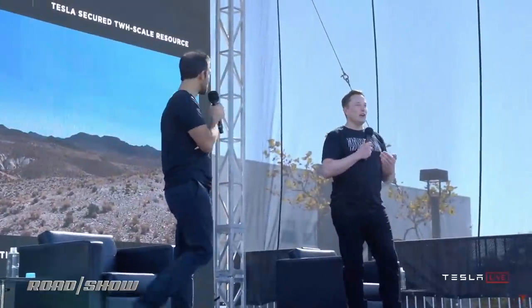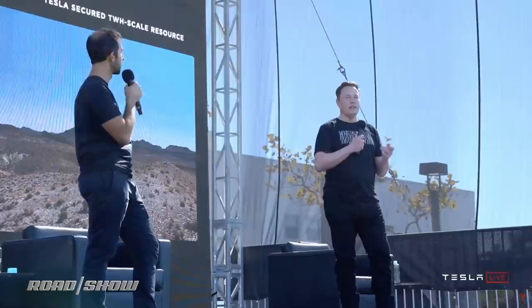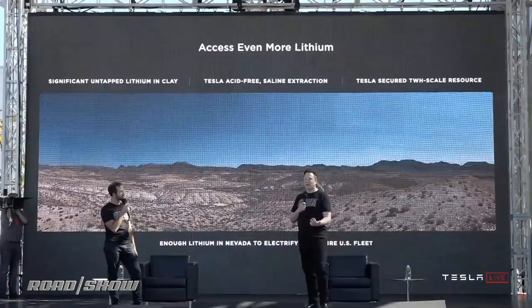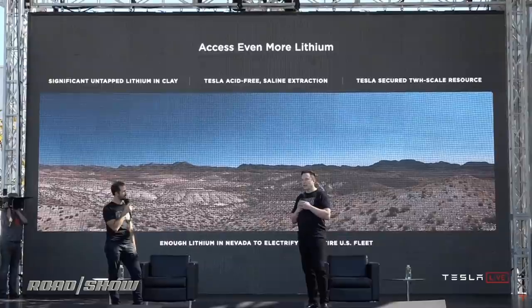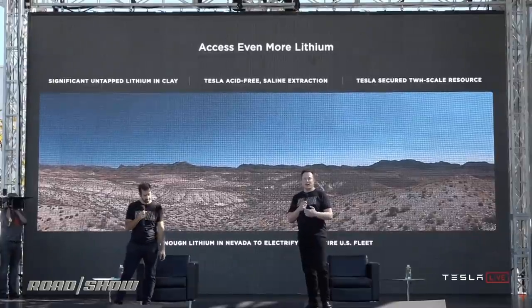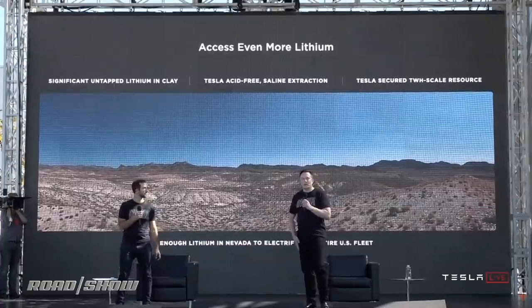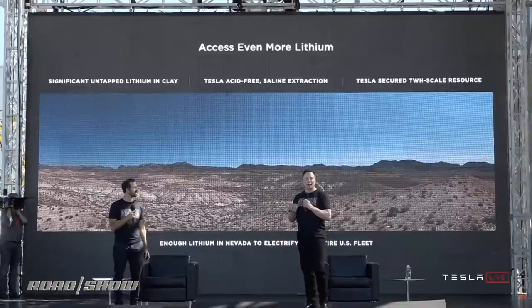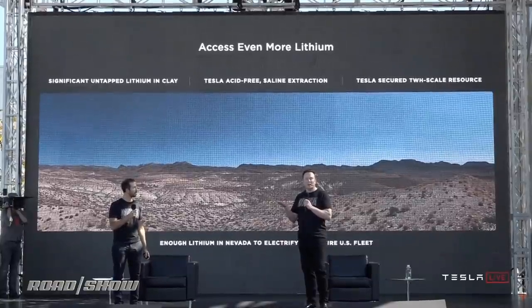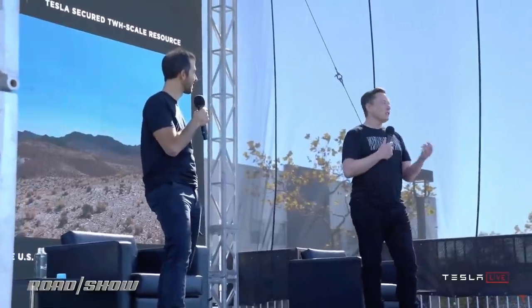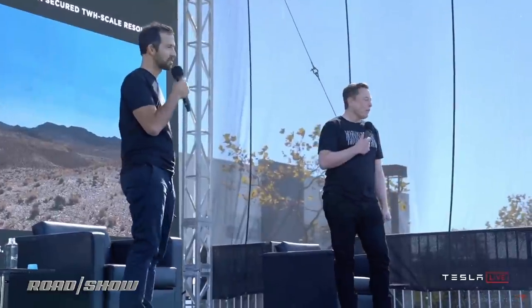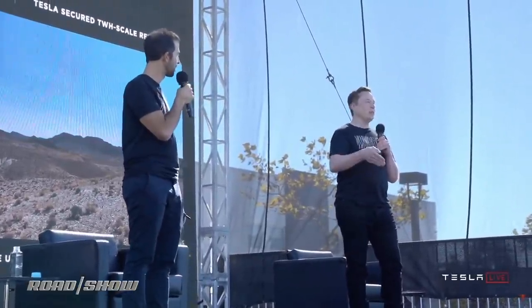But it is important to say, what is the smartest way to take the ore and extract the lithium and do so in an environmentally friendly way? And we actually discovered, looking at it from a first principles physics standpoint, instead of just the way it's always been done, that we can use table salt, sodium chloride, to extract the lithium from the ore. We actually got rights to a lithium clay deposit in Nevada. Over 10,000 acres. And the nature of the mining is very environmentally sensitive, in that we take a chunk of dirt out of the ground, remove the lithium, and then put the chunk of dirt back where it was.